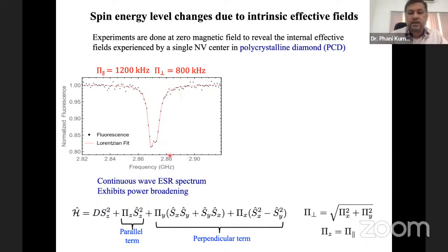And here you see the continuous wave ESR spectrum at zero field, and we have this splitting and also this shift of the energy levels. I would also like to mention that because the stress response and the electric field response are very small, we have to perform these experiments at zero magnetic field. That is very crucial to measure the effects of these intrinsic effective fields in the diamond lattice.